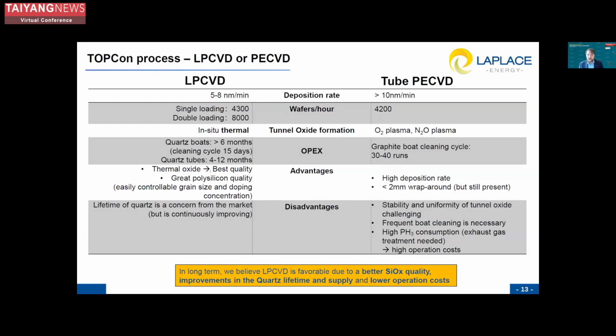But I would like to mention here that we are currently already having some tools in test in the manufacturing lines where we use double loading, and this will bring the wafers per hour up to 8,000 wafers per hour, which makes the throughput extremely favorable for the LPCVD compared to PECVD tubes. For me, I think the biggest difference is on the tunnel oxide formation, where in the LPCVD we work with an in situ thermal silicon oxide, and in the tube PECVD we need an oxygen plasma or an N2O plasma to build our silicon oxide layer.